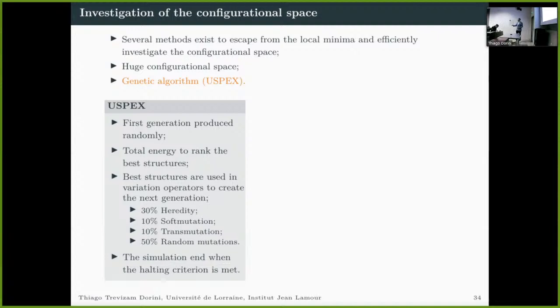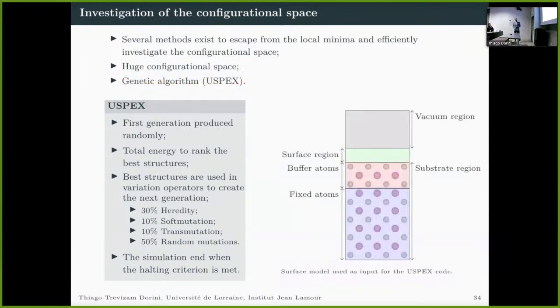First, we randomly generated the structures, and we ranked the best structures of this first generation according to their total energies. After, we used some variation operators to create a new generation based on the old one. We used these four variation operators to change between generations. The simulation ends when the halting criterion is met, basically when the next generation is the same as the old generation. But to be more specific, here is the system that we used.